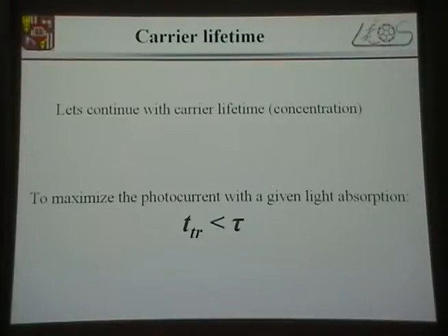So, carrier lifetime and the concentration. With the known absorption of the solar cell, we want to fulfill this condition if we want to maximize our photocurrent. What it means is that the charge carrier transit time through the film must be much faster than the carrier lifetime. If that's not the case, the charge carrier will recombine on the way and will not fully contribute to the photocurrent. Therefore, your IPCE or your EQE will go down due to recombination.